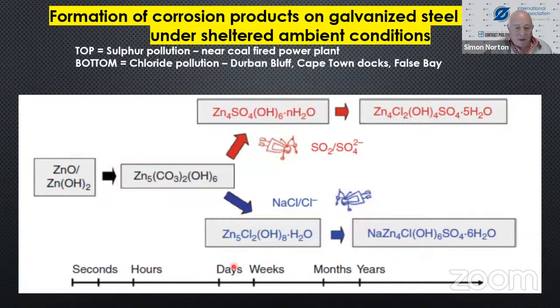And if you look at the bottom here, you'll see that this form starts to form within days, this material within weeks, and this finally within months and years.